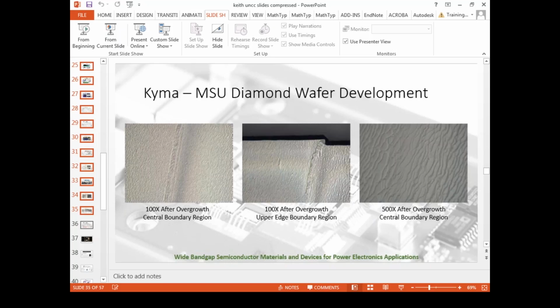Another approach is to take the really tiny high-quality material and then grow CVD. You can make it thicker and then flip it over and make it thicker and flip it over and make it thicker. That seems worse than watching paint dry. And then the third approach is to take polycrystalline material, which you can get in pretty large area. For instance, II-VI Corporation supplies that. And we've seen that material because we're actually growing some GaN on that diamond. If you could enhance its properties to where it was of electronic grade.